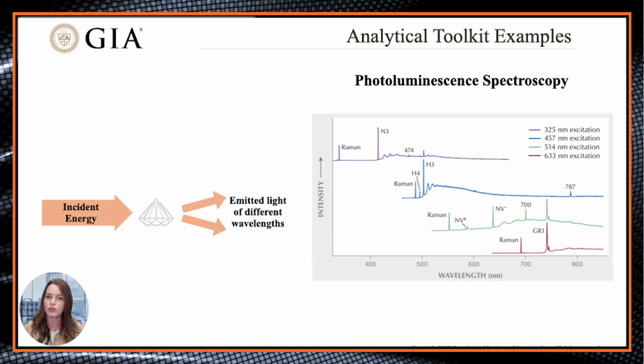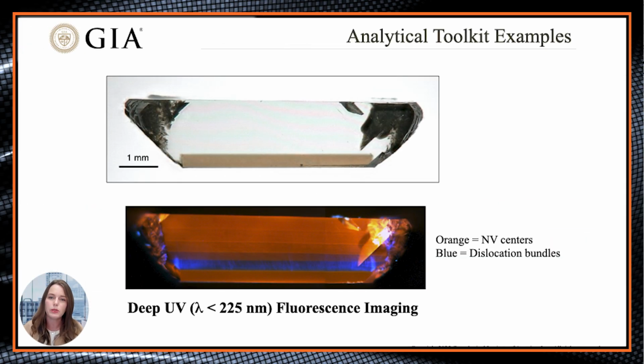Absorption spectroscopy is key for evaluating diamond for optical transmission applications. Incident light may also excite defects, which then emit light known as luminescence. We can detect these defects through high-sensitivity spectroscopic techniques, such as photoluminescence, as well as deep UV fluorescence imaging, which can reveal their distributions and the intrinsic growth patterns in the material.